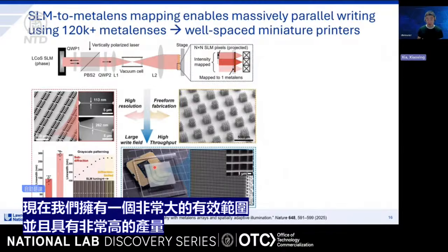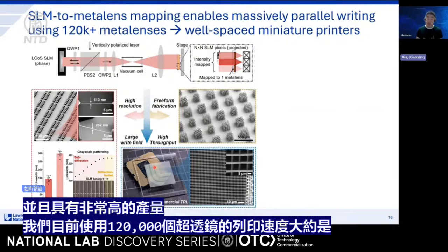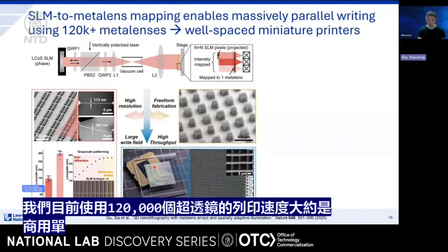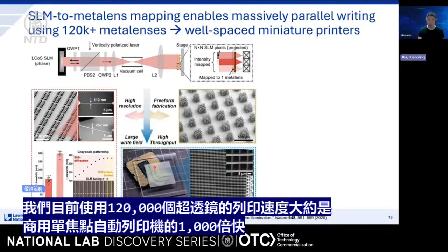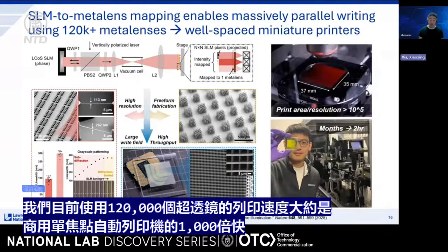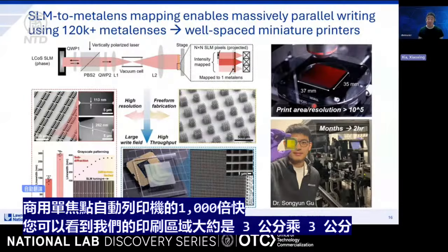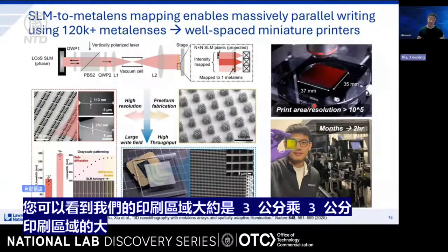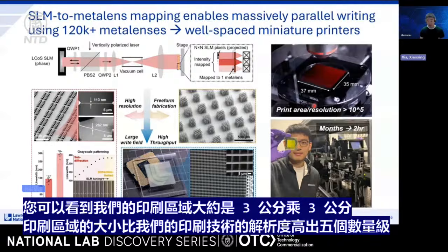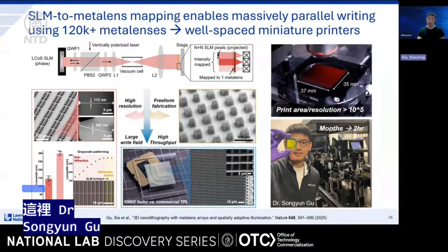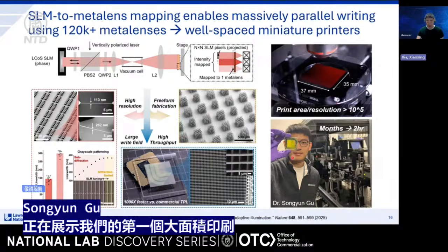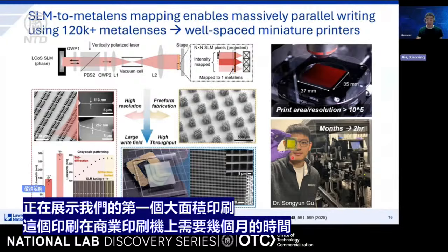So our current printing speed, using 120,000 metalenses, is about 1,000 times faster than a commercial off-the-shelf printer that has only one focal spot. And here you can see that our printing area is about 3 centimeters by 3 centimeters. The size of the printing area is 5 orders of magnitude larger than the resolution of our printing technique. And here, Dr. Song-Yin Gu is showing our first large area print. This print would have taken a few months on a commercial printer, and it only took us 2 hours to print.